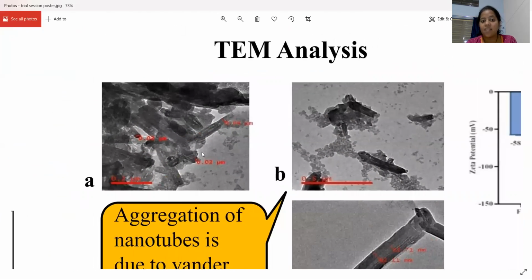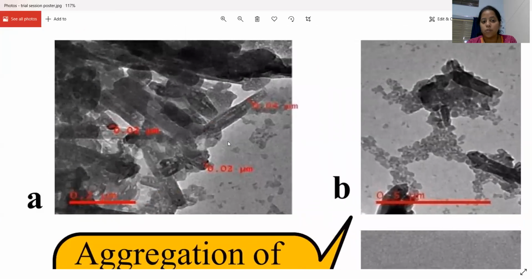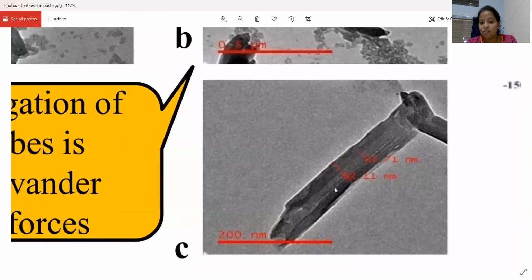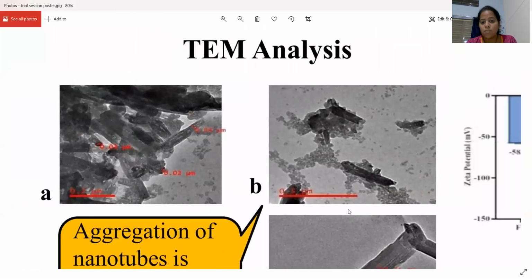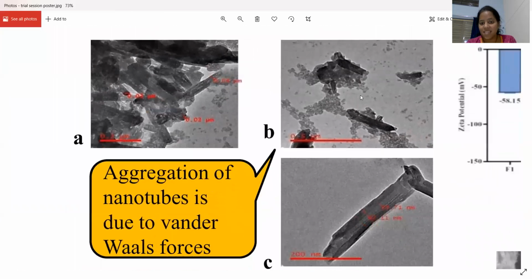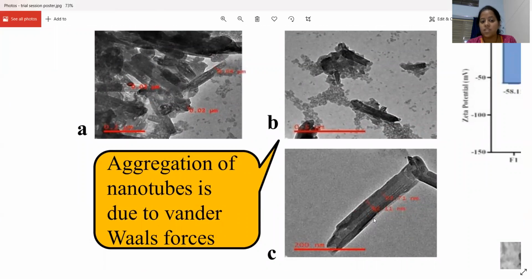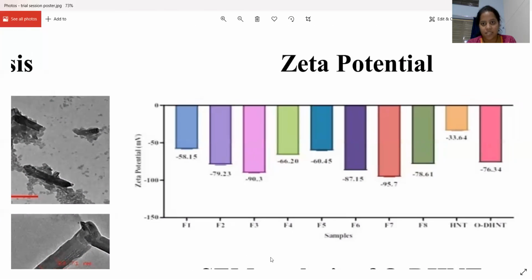Halloysite nanotubes are characterized by a hollow nanotubular structure with an open-ended lumen, with lengths ranging from 400 to 1000 nanometers. Upon doping, in the F3 sample we could observe that the length of the nanotubes was enlarged to 600 nanometers and a layer of gamma-MPS was wrapped onto the surface of HNTs as the surface had become rough. The main observation that we could find is in the F5 sample, wherein the aggregation of the nanotubes is due to the presence of van der Waals forces.